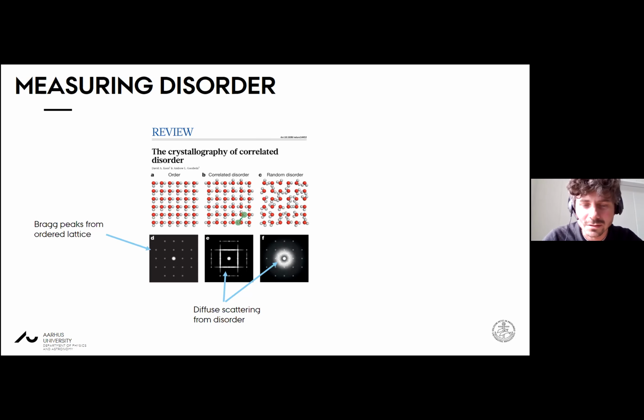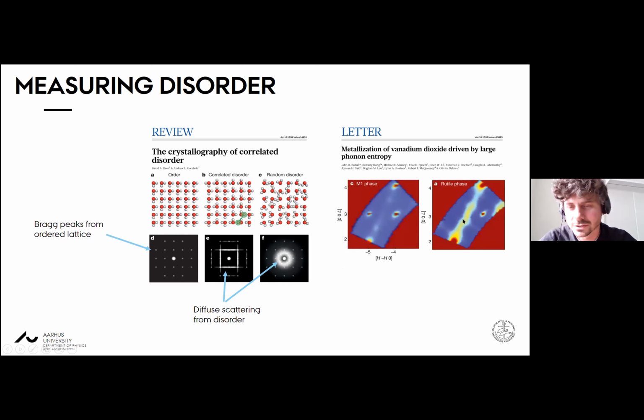So we need to look at this diffuse scattering because this tells us how the disordering is going in vanadium dioxide. And so here I just show that you can do this statically in vanadium dioxide. And what you find in the low temperature phase is the system is very harmonic, which means that there's very, much like case A, little disorder in the system, entirely ordered. And when you go into the metallic phase, the system is behaving more like this correlated disorder. And that's because the metallic phase of VO2 likes to form dimers. It prefers to fluctuate along those directions than others.